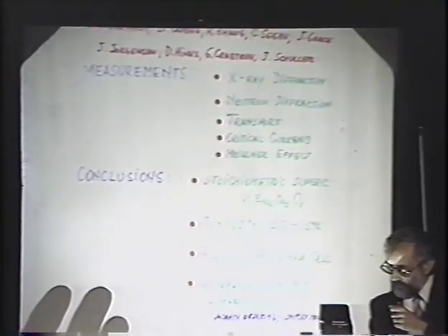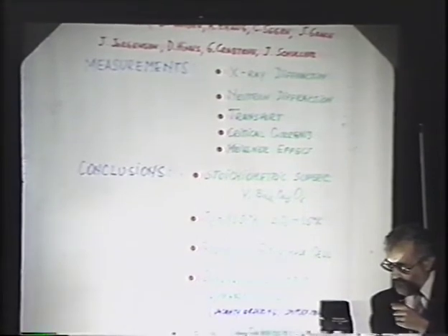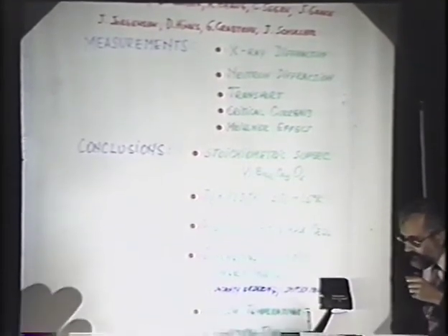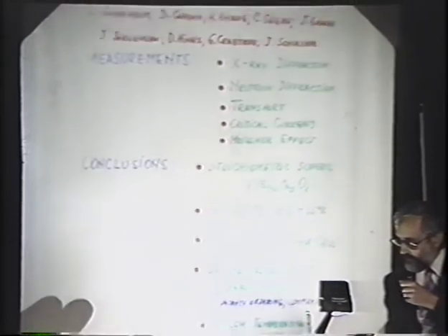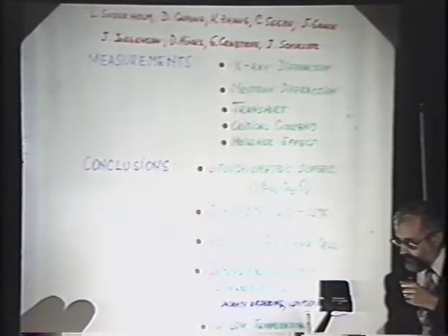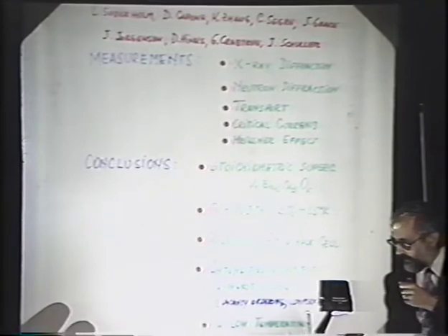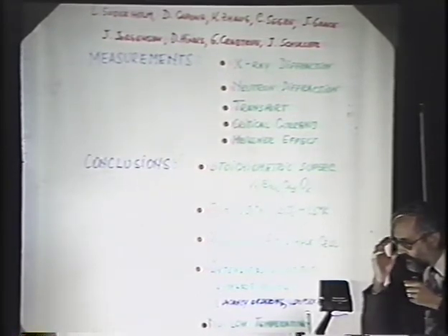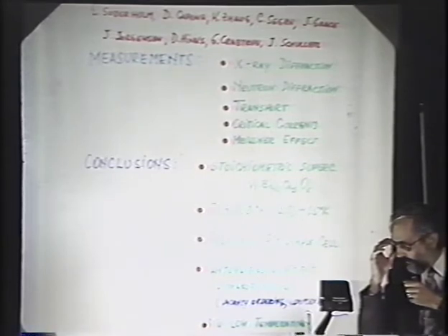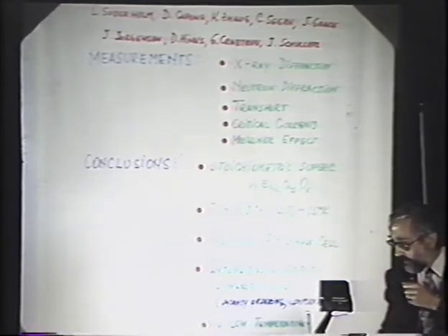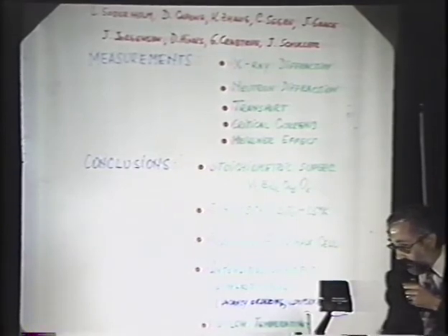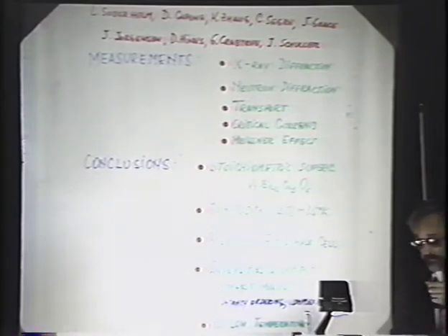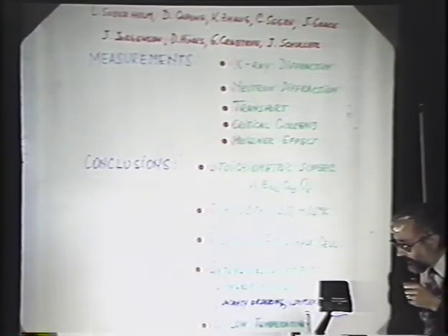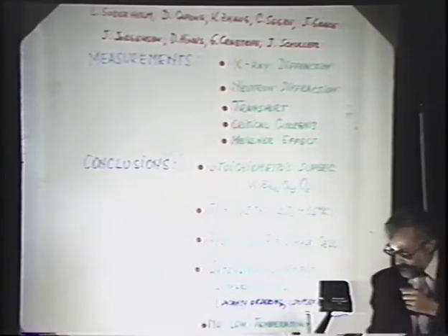The single phase is yttrium, barium 2, copper 3, oxygen x. We have on this material X-ray diffraction, neutron diffraction, transport critical currents, Meissner effects, all of the things you have to have. What I want to emphasize is that we have some very detailed high-resolution neutron diffraction data on these materials, which is being analyzed for the structure. At the moment I would not say we have the structure, because the neutron data does not fit any simple models, although I would like to see in more detail the model that Paul Chu showed, so that we could apply it and see how it works out with the neutron data as well.